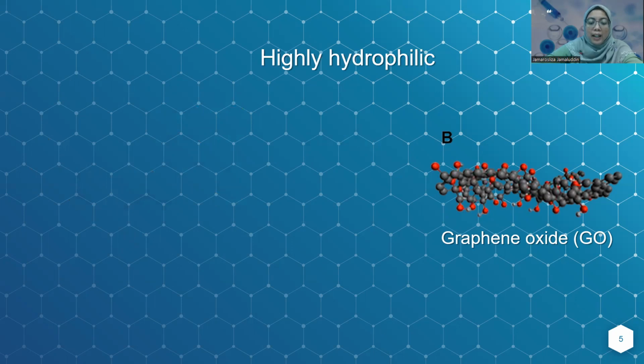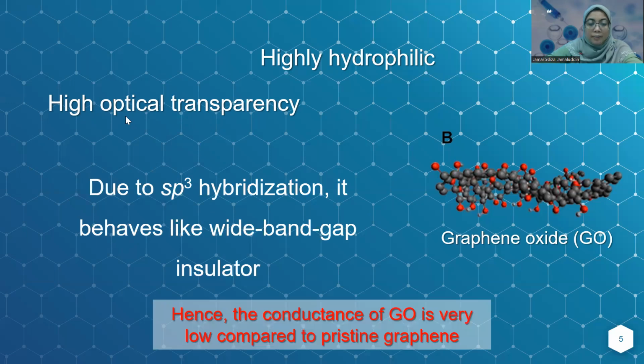Graphene oxide is highly hydrophilic, meaning it readily interacts with water and other polar solvents. This is due to the presence of oxygen-containing groups such as hydroxyl and carboxyl groups on its surface. These can form hydrogen bonding with water molecules. Besides that, graphene oxide also has higher optical transparency. However, graphene oxide has low conductance due to the introduction of oxygen-containing groups.